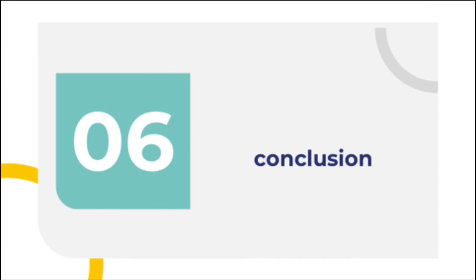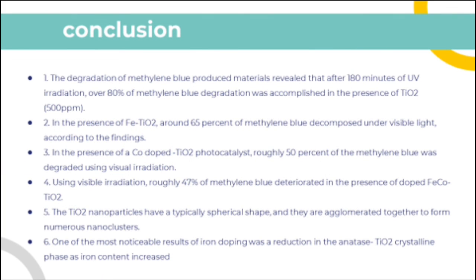The best result we got was around 65% of methylene blue degraded in the presence of Fe-doped titanium dioxide using 1 gram titanium dioxide, sol-gel method, calcined at 450 degrees Celsius under visible light. Around 50% of methylene blue degraded in the presence of 0.6 gram cobalt-doped titanium dioxide under visible irradiation, and 47% of methylene blue degraded in the presence of 0.6 gram Fe and 0.6 gram cobalt doped titanium dioxide under visible irradiation. Thank you.